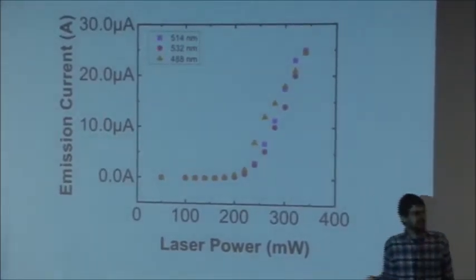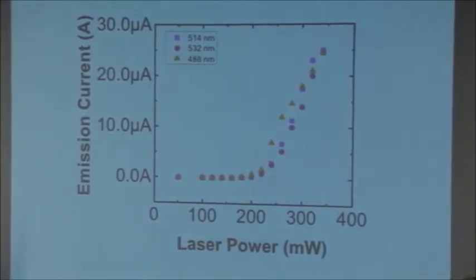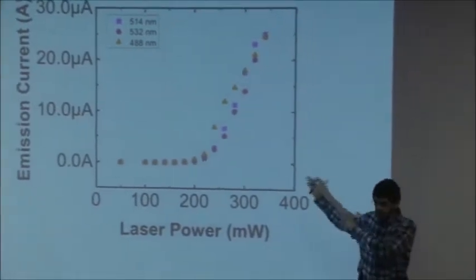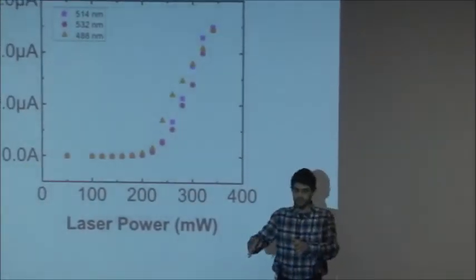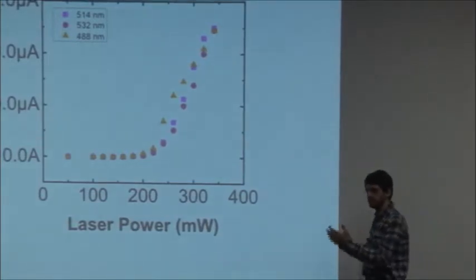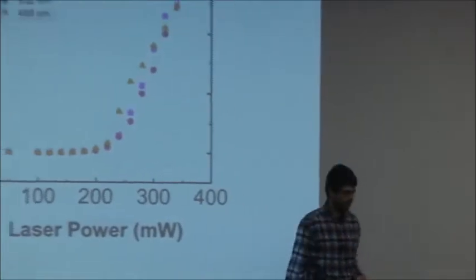And that fits the thermionic emission law proposed by Richardson 100 years ago. That fits it pretty well. And when you do the temperature measurement and electron emission current measurement, you put them in Richardson's equation, and all these fit quite well. So it's clear that there's a dominant electron emission component here that's thermionic, and that temperature is high, and so on. So let me show you how it works.